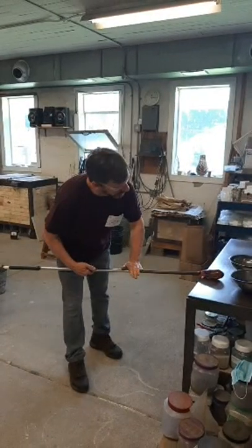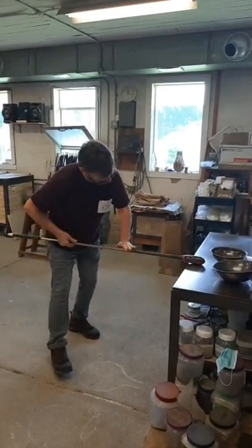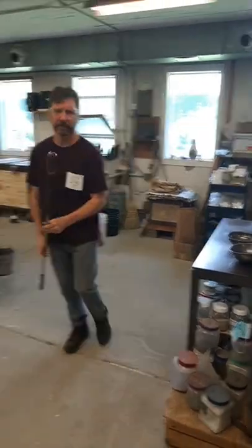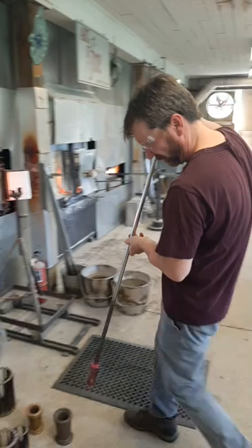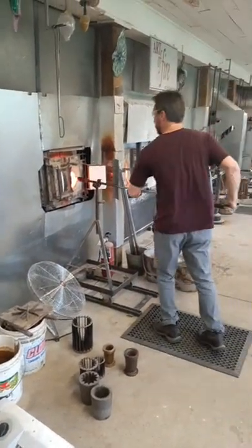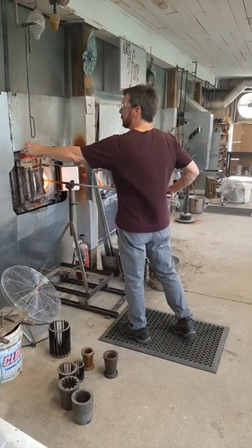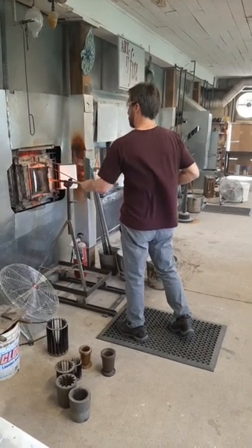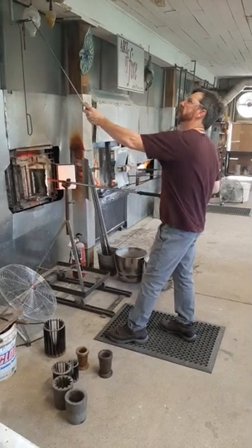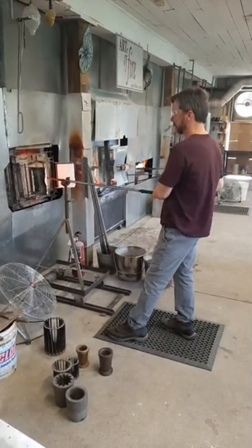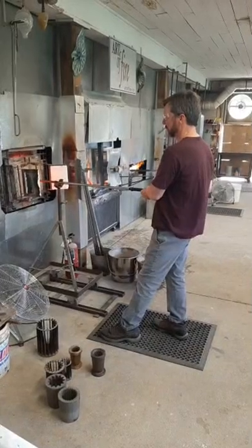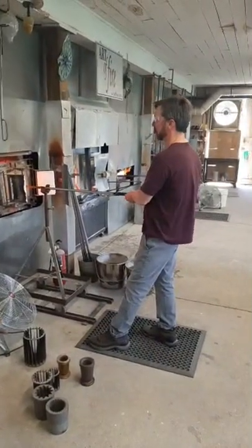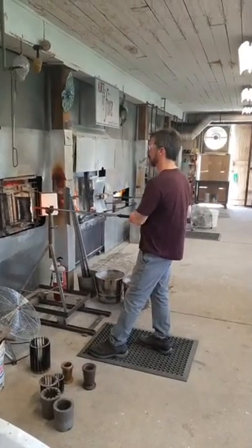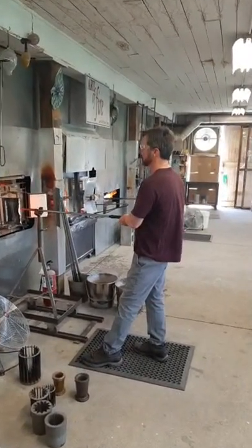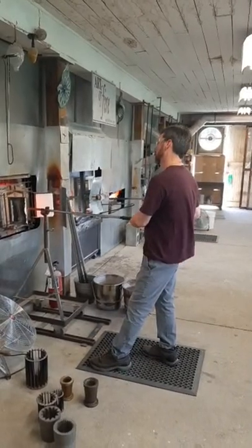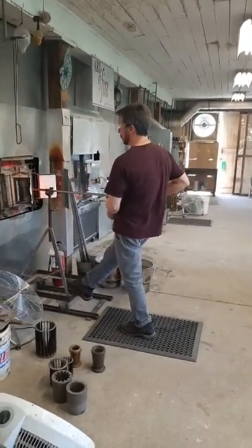So one thing that's a little bit different about this particular mold is the glass blower wants to make sure that the bubble goes very far down into the gather of glass, right down to the tip. Because if there's a thick spot of glass, again on the gold and blue. So he put blue on initially, quite a few coats of that. Then he put the gold over top of that. Now when he goes into the optic mold and blows out, the blue is going to start pushing up a little bit. But as he blows the piece out later on, the blue is going to push the gold aside a little bit.